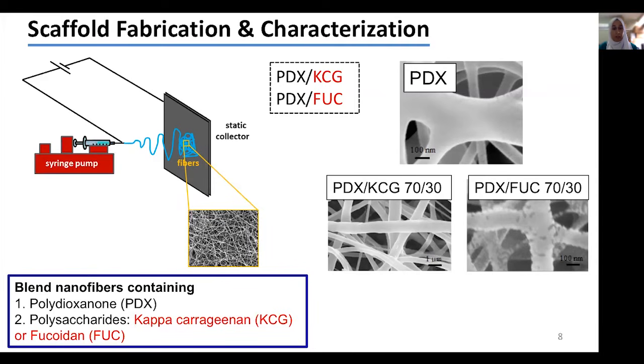So we basically fabricated blend nanofibers consisting of PDX and KCG, or PDX in combination with fucoidan. And the ratio of PDX to the seaweed-derived polysaccharides was varied, such that we had a range of different compositions. The blend nanofibers were characterized in depth in terms of their physicochemical properties.